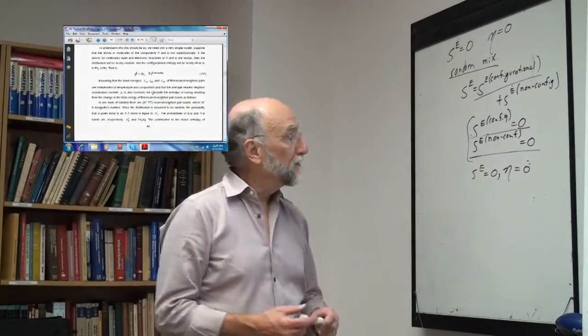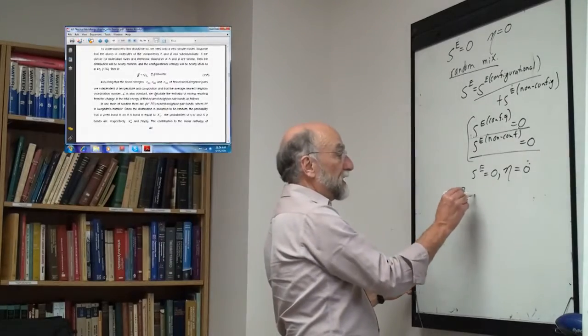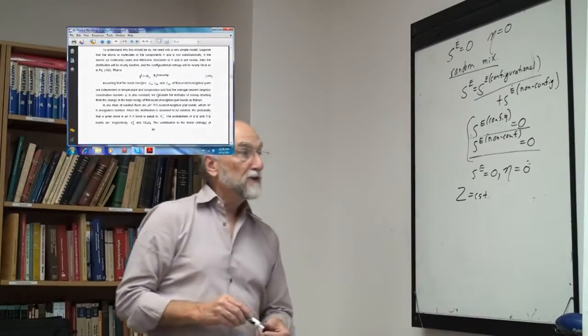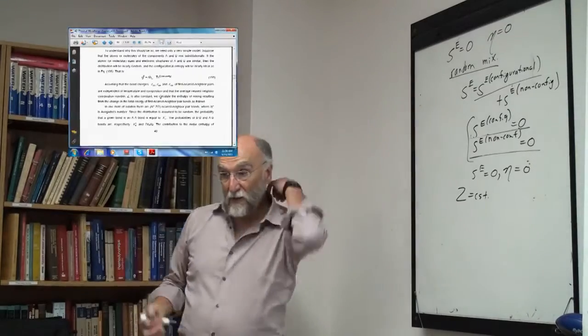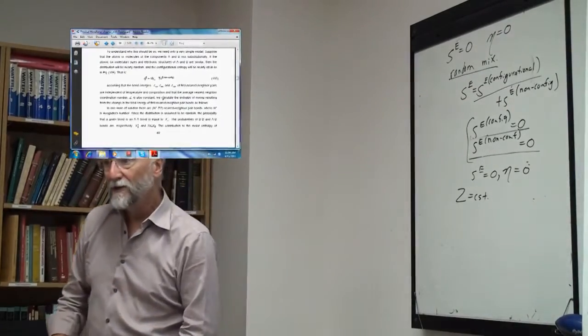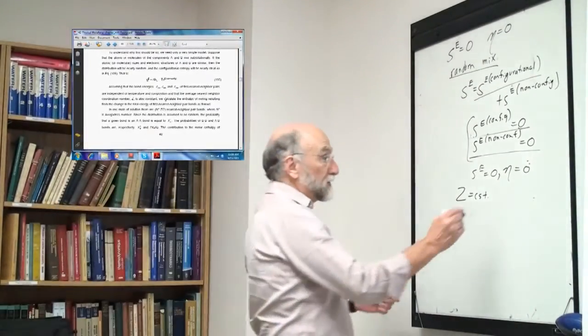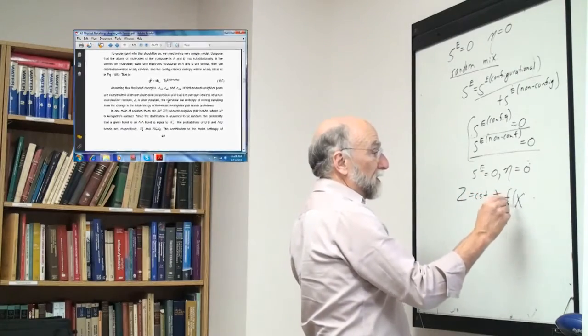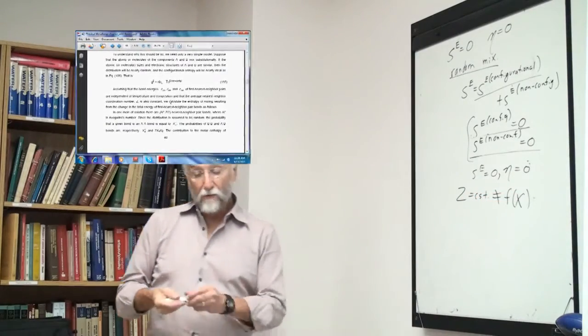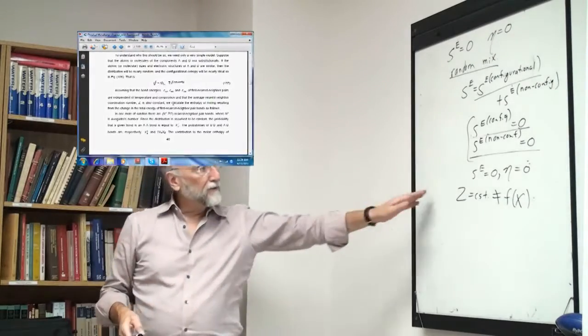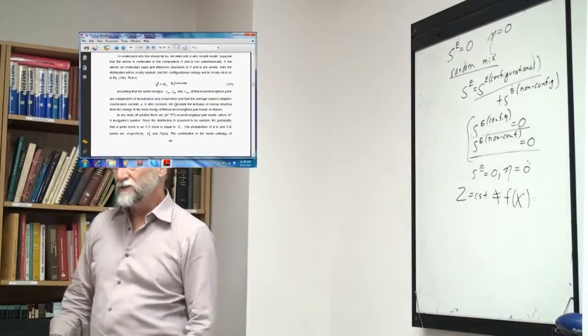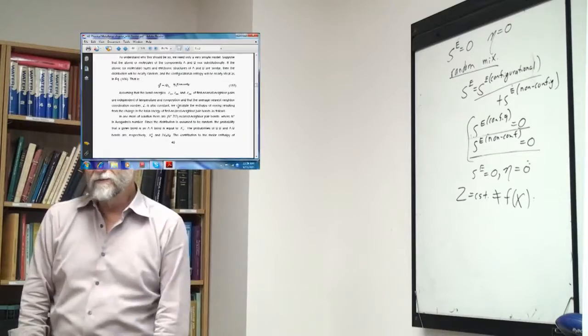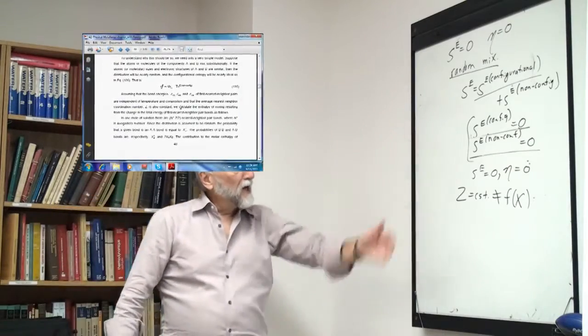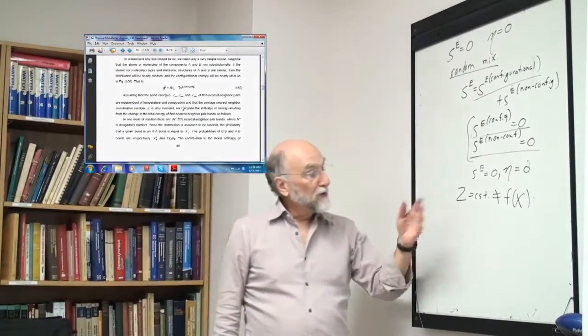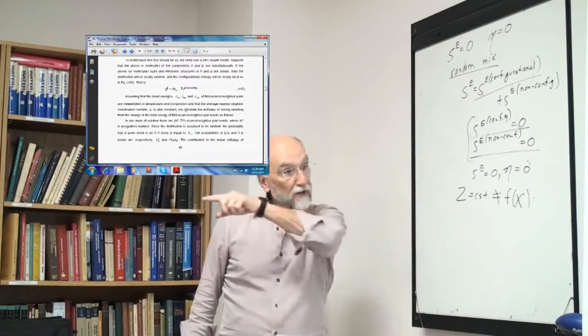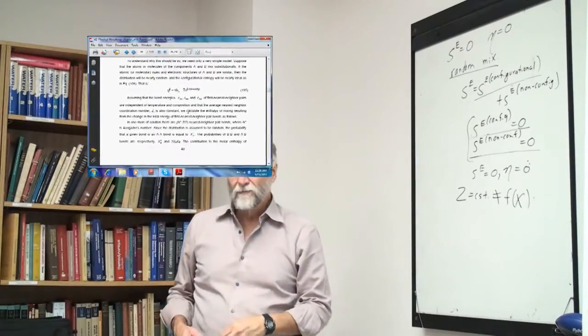I'm also going to make even more simplifying assumptions that Z is constant. Z is the first nearest neighbor coordination number. That's the number of nearest neighbors around a central atom. We assume that's not a function of composition. So as you go from pure A to pure B, the first nearest neighbor coordination number stays the same. If you're mixing copper and gold liquid, the first nearest neighbor coordination number is around 12, and we assume it's constant, independent of the composition.